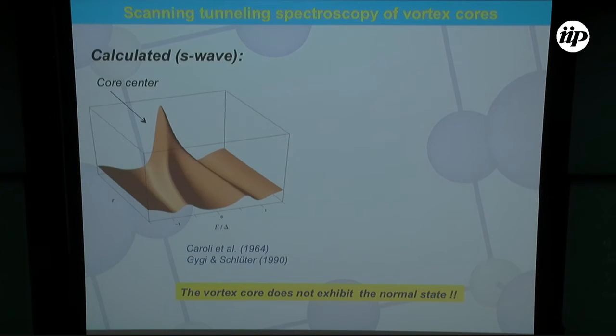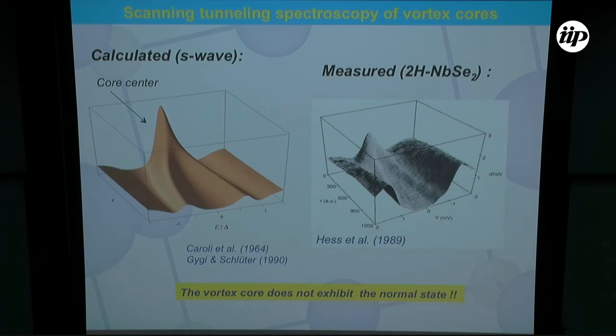As a consequence, the vortex core center usually reveals a zero bias anomaly, which actually consists of a set of bound states which are very closely spaced. And when you go from the center to the outside of the vortex, you get the splitting of this peak, due to the fact that the angular momenta increase and the spectral weight is pushed towards higher energies. So this is the calculation. And of course, the first measurement in the 90s by Hess really showed the expected behavior for a BCS S-wave vortex core.